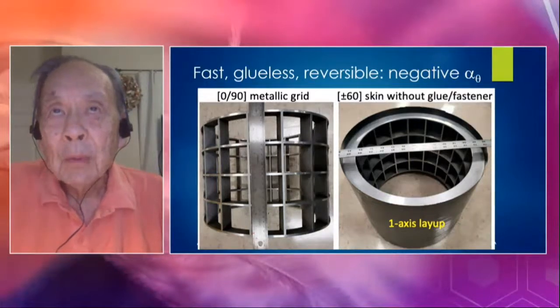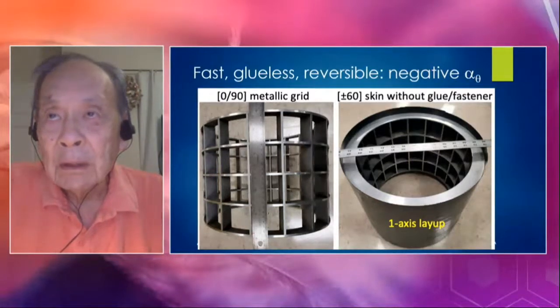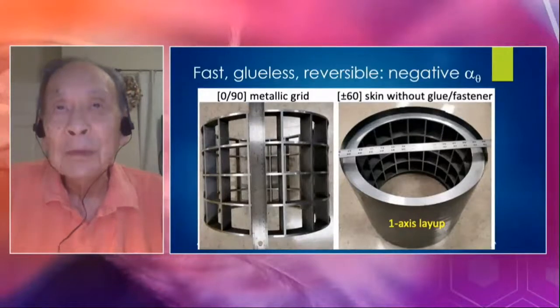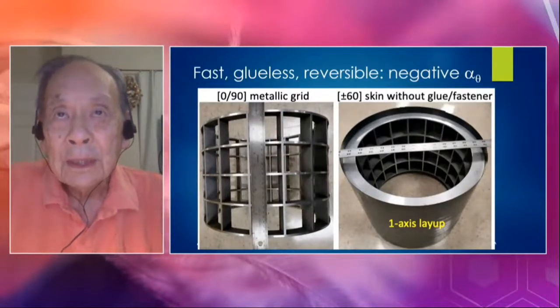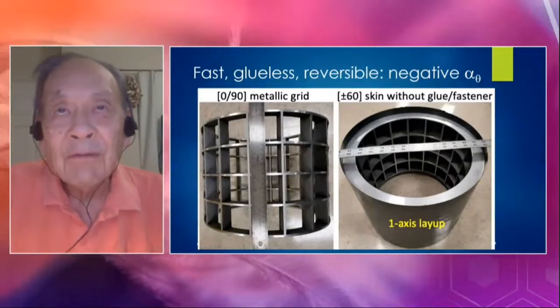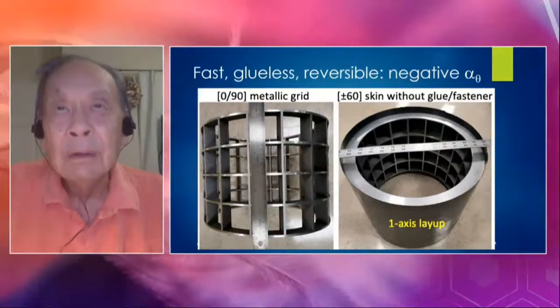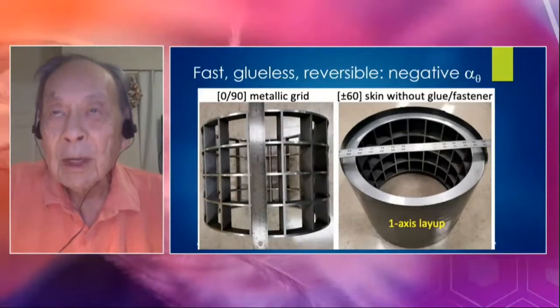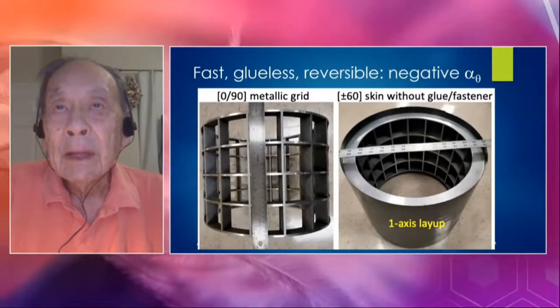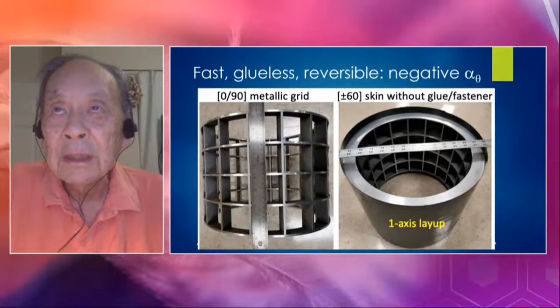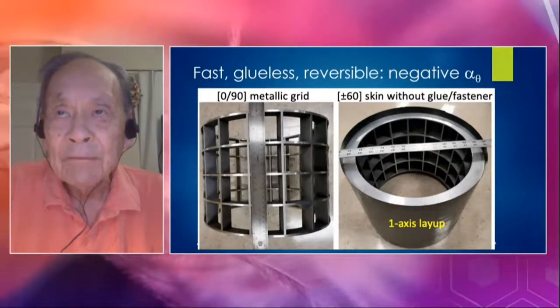So finally, we have a demonstration model showing the grid, and we are proposing to use a metallic grid, and this is easy to manufacture using a water jet or wire shaping. And then we take advantage of the negative thermal expansion of the skin at plus or minus 60, so that you can assemble this by chilling both components and putting them together, without glue and without fasteners.